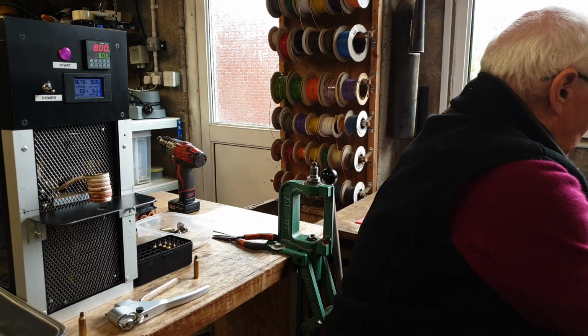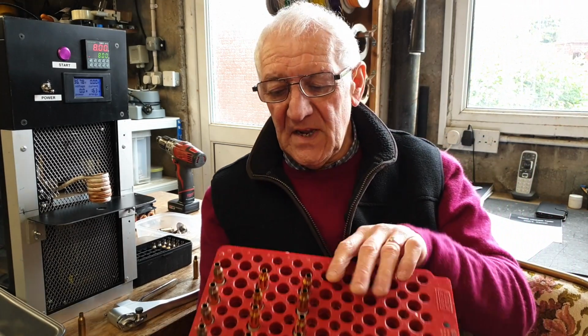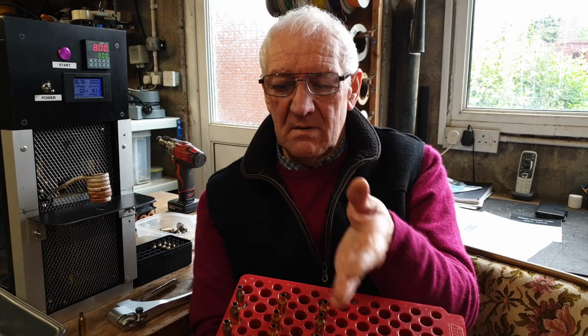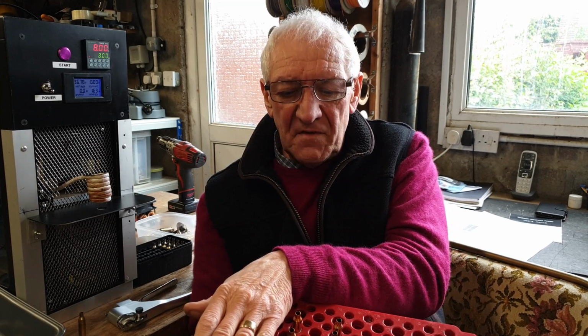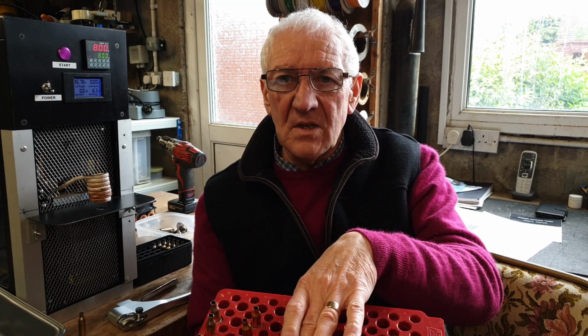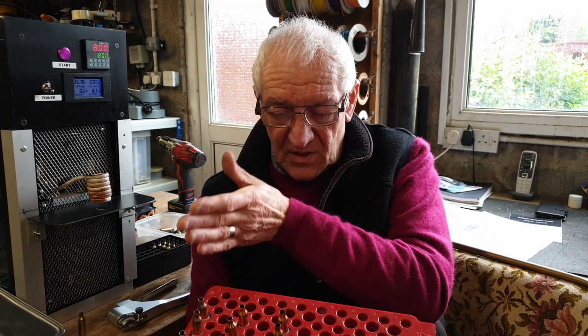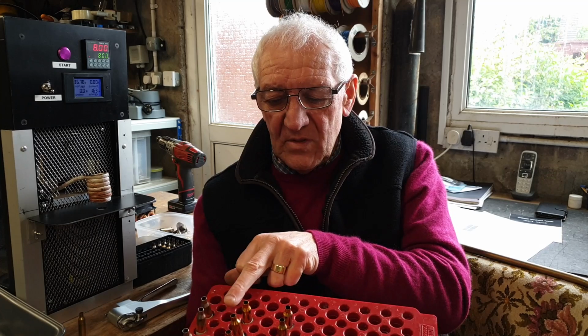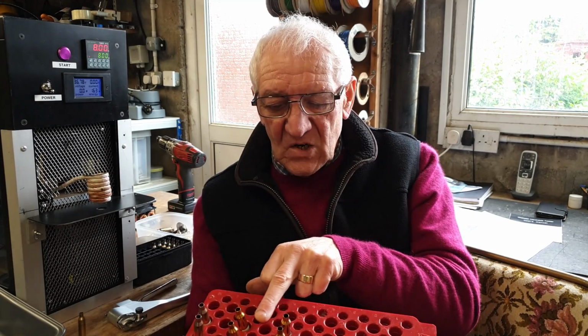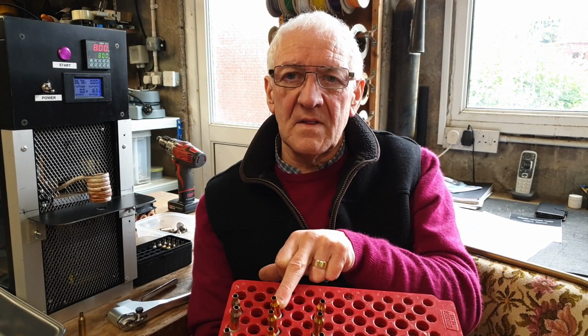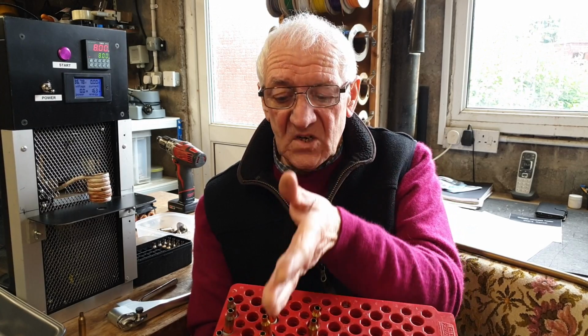The other thing was that the 3 different sample groups broke into 3 clear hardness bands. This was soft, this was significantly harder, and this was a little bit harder still. So they were nicely distinct. There's a big gap between the new and the ones fired, and a somewhat smaller gap between the ones fired and the multiple fired, but again, still a distinct gap.